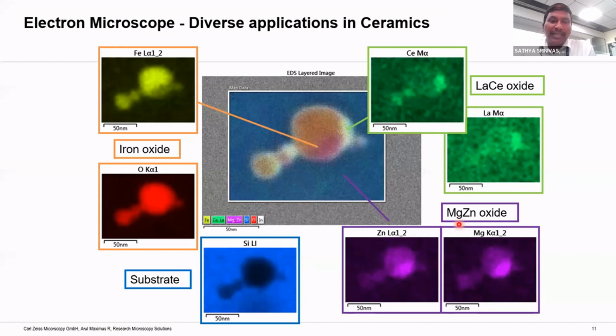Even at lower kVs nowadays, the technology allows this, because samples cannot sustain the higher kV, and to get an EDS signal, you need to apply higher kVs, like more than 15 kV. This is the understanding people have. But now with the latest technologies, even with a lower kV like 5 kV or 2 kV, you can pick up the EDS signal and identify those elements wherever they are present. But the sample preparation for such things is a little bit typical. You can clearly see the distribution, the mapping of all the individual elements at very low kV.